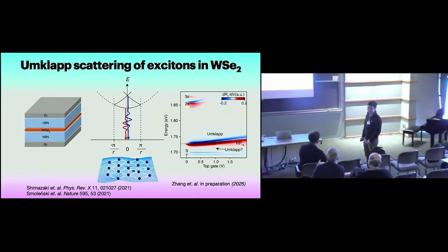Splitting of the attractive polaron resonances seems to be substantially larger, compared between these. At first we thought it's due to the effective mass, although we don't have a fully theoretical understanding of how the effective mass changes for the attractive polaron and the repulsive polaron, because that affects the slope of it. We find that this Umklapp feature is very close to the bare exciton mass, agreeing pretty well with the DFT calculation. This one somehow shows a smaller mass.